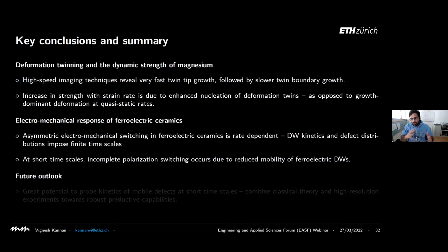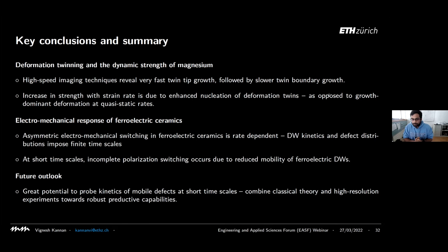And we observed a lot of interesting phenomena during cyclic experiments where you have asymmetric switching and then you have a rate dependence in the switchability of these ferroelectric ceramics. We connect that to domain wall kinetics and we're still in search for the exact mechanisms for why these rate effects occur. And we discuss some future perspectives of how we can use this idea to move forward. So I hope I've gotten a lot of you excited about this problem, and I hope to find a lot more future collaborators on some of these problems.